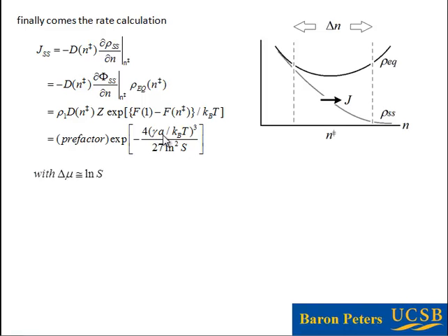My barrier size is modulated by the interfacial free energy and the area per volume, divided by the temperature, and then I cube those things. So the slightest change in the interfacial free energy causes a big change in the size of this barrier. And the slightest change in the supersaturation also causes a big change in this barrier.